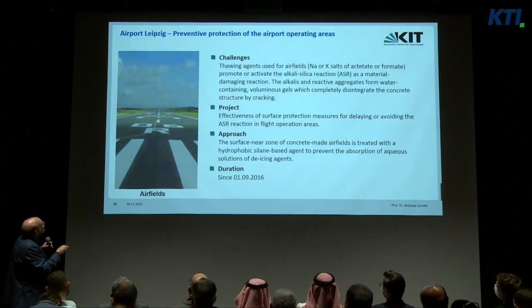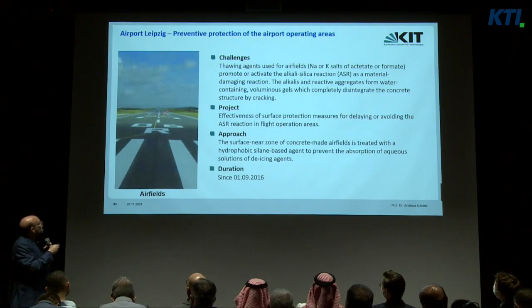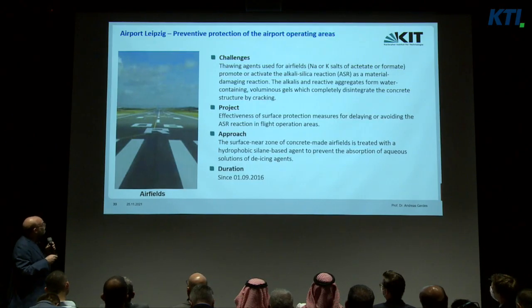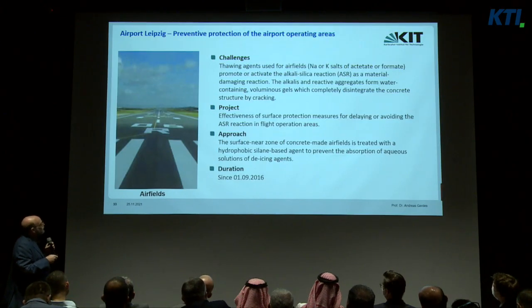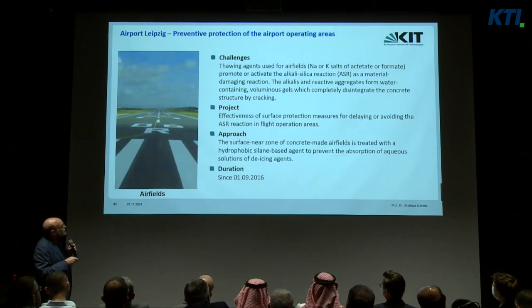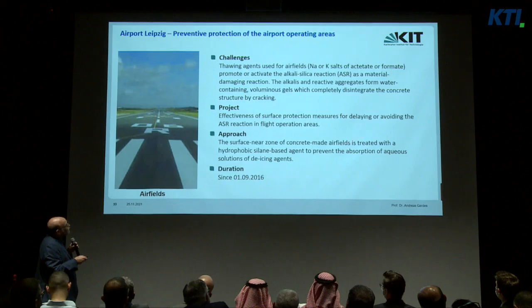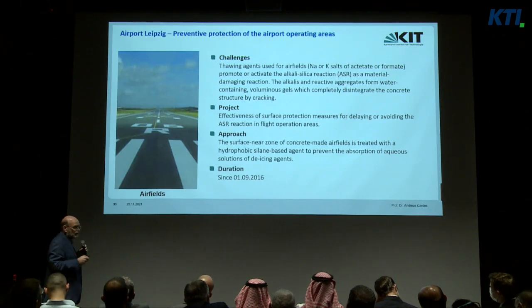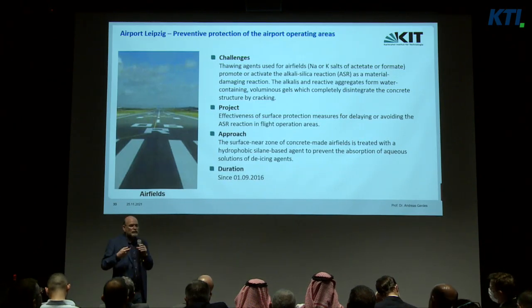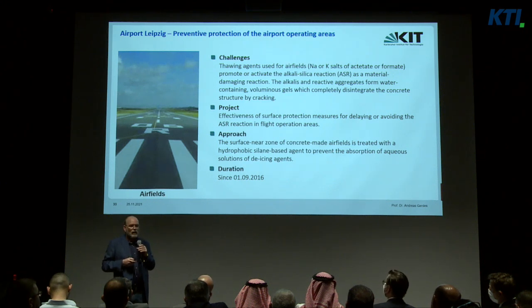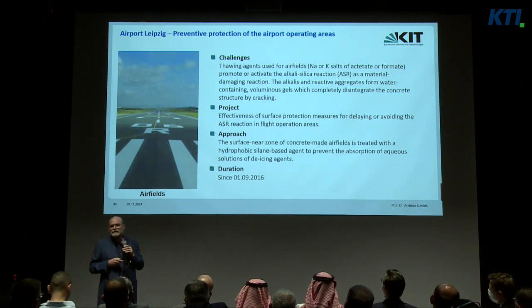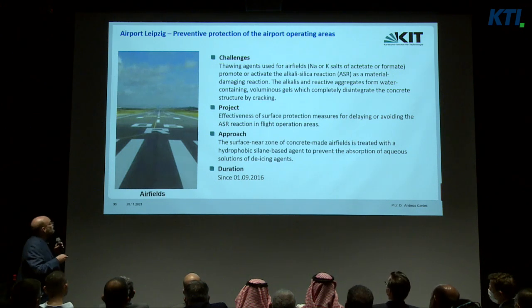This is already the protection of the concrete of these airfields against ASR, using a hydrophobic silane-based agent to prevent the absorption of aqueous solution of the de-icing agents. We did it some years ago, and it works very well up to now. And I think it will work for the next 20 years. Then we have to redo it.